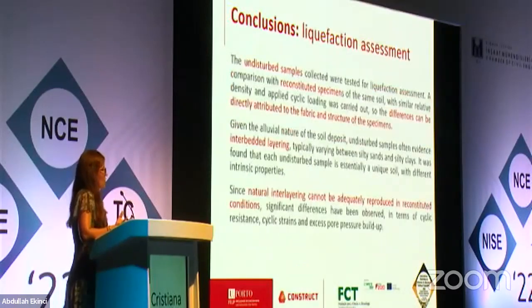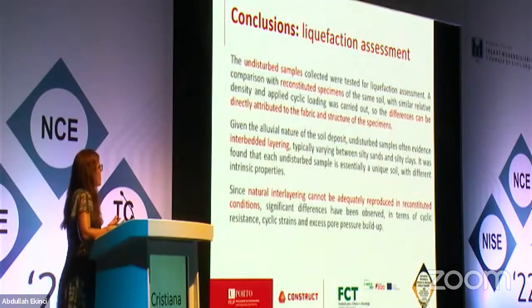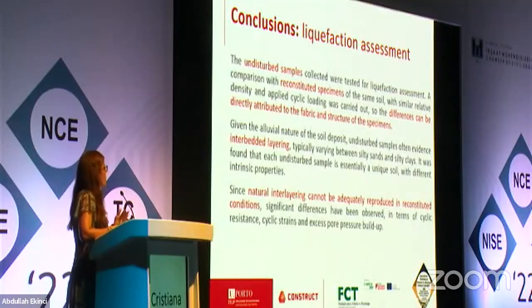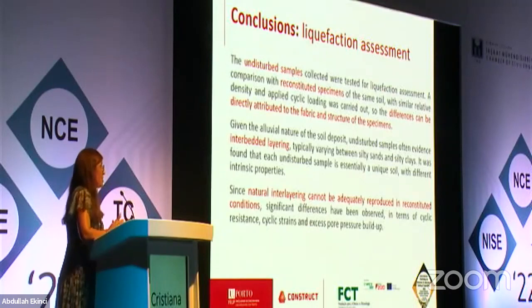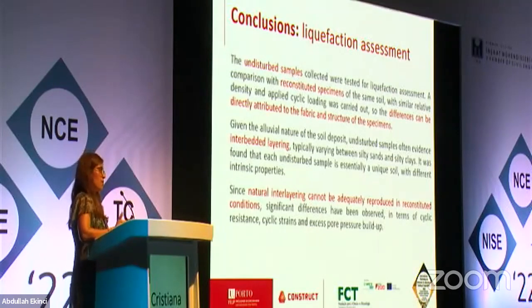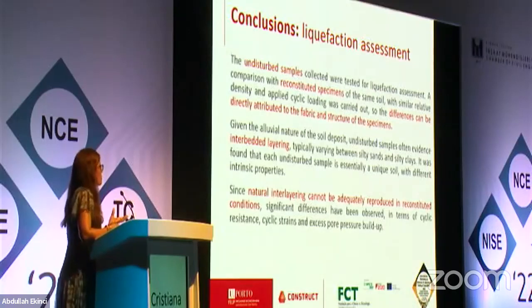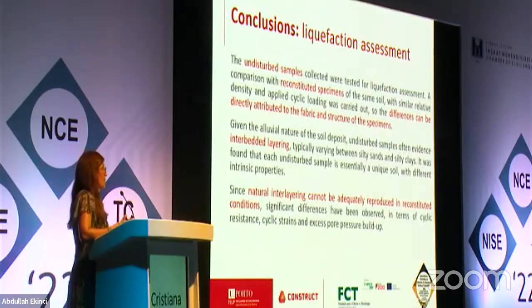In terms of the liquefaction assessment that we are focusing on here, the undisturbed samples were tested, and then compared with the reconstituted specimens at the closest possible condition, that is with the same soil, a similar relative density, and with the same applied loading, so that these differences can be directly attributed to the fabric and the structure of the specimen.